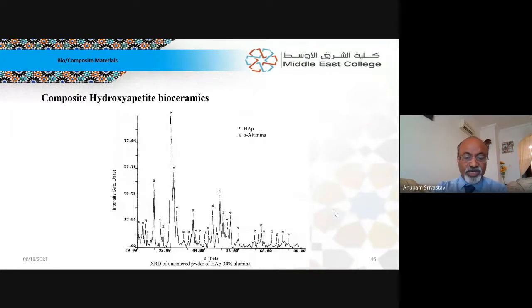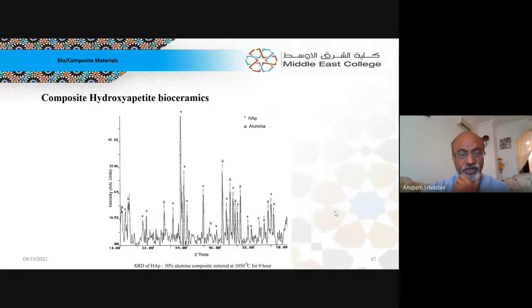You can see there is a peak at 33 or 35 degrees, and that is the characteristic peak of HAP, and the smaller peaks are of alumina. Those of you who are doing mechanical characterization using XRD know it, so we don't have to go into detail. Once they are heated, you can see there is a change. Here it is like this, now it is like this. So we have to identify with the intensity peaks which peaks these are and what they correspond to. Then what material has been formed, whether there is a decomposition of hydroxyapatite and a chemical reaction taking place, and so on. This is how it is characterized.